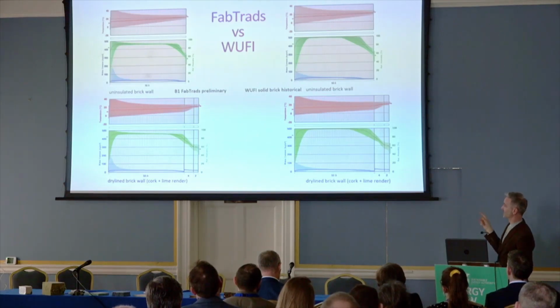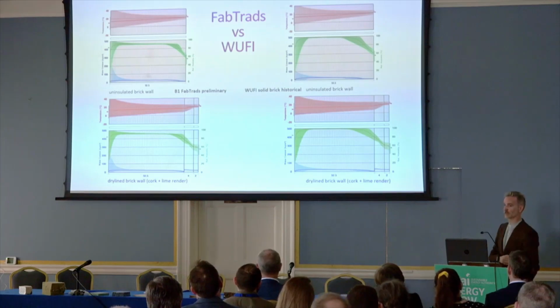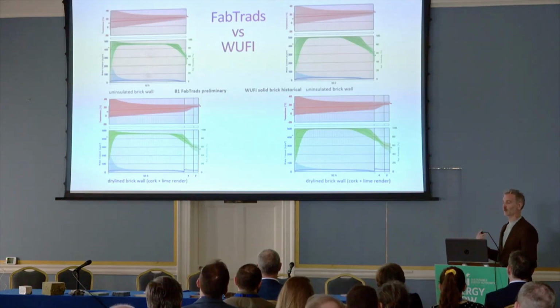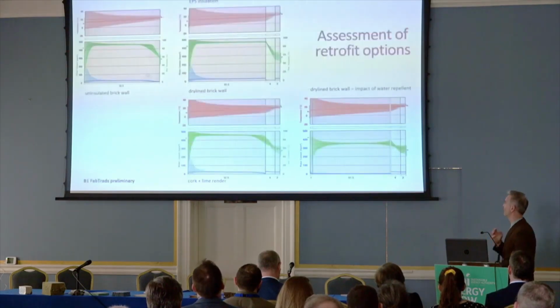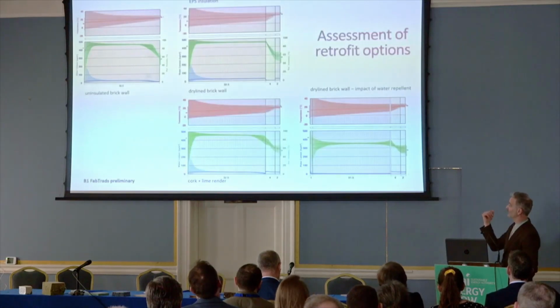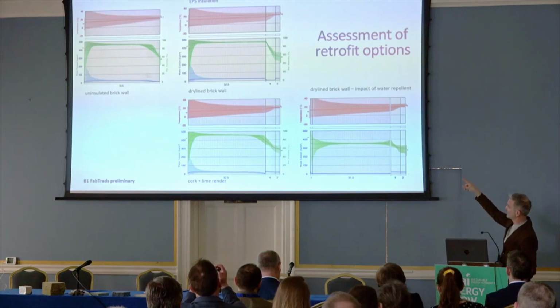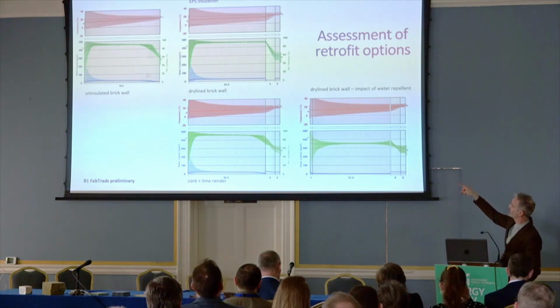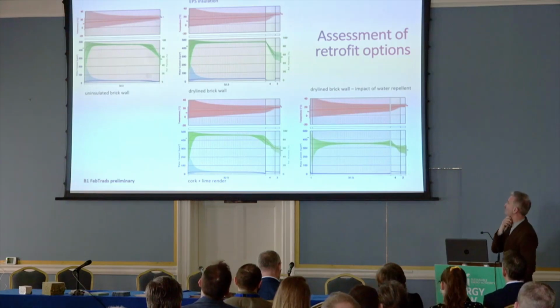And we are seeing some differences. All we can say at this stage is we are seeing some differences in moisture response using the Irish parameters compared to using the standard WUFI parameters. We need to really complete the data set of parameters before we can draw any major recommendations from this analysis. But we have been playing around with different insulation types. So looking, say, at the green in this case is the relative humidity, and the blue is the water content. The red is the temperature through the wall sections.